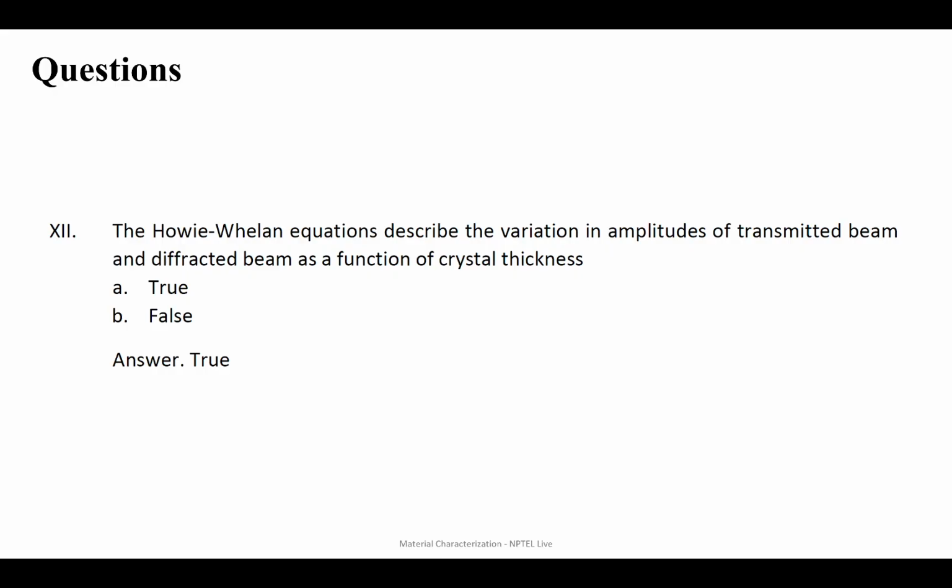So this is true. The Howie-Whelan equations, which combine the scattering of electrons from the transmitted beam and from the diffracted beam, describe the amplitude as a function of thickness.